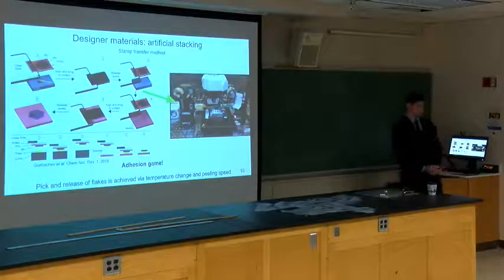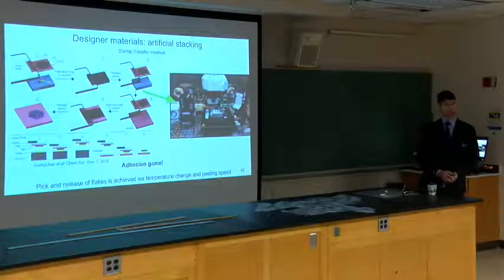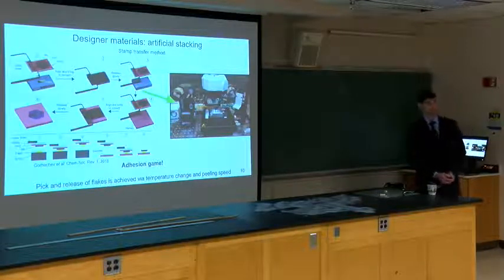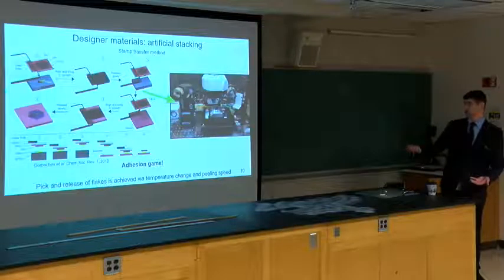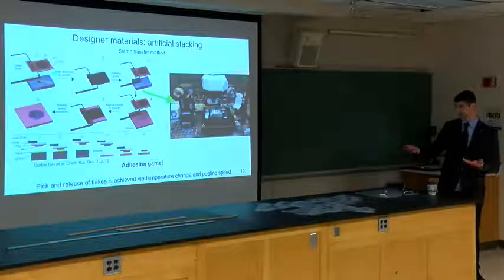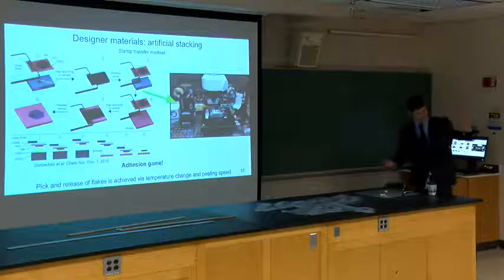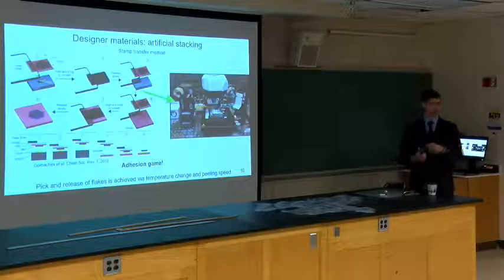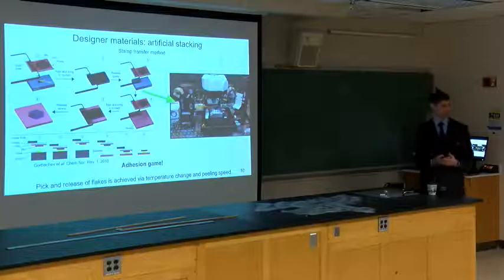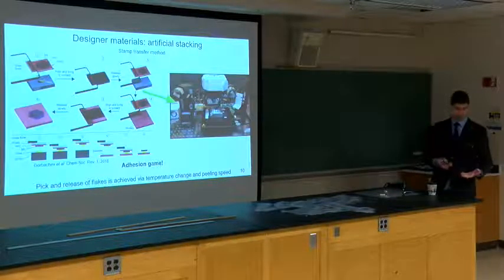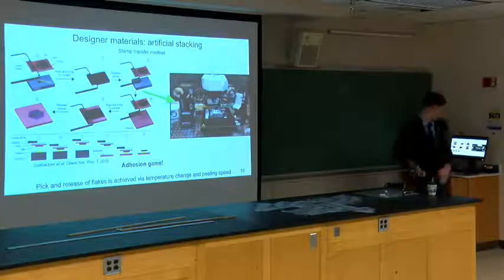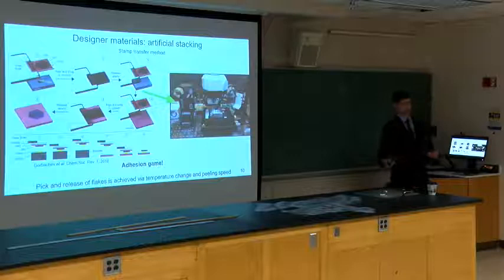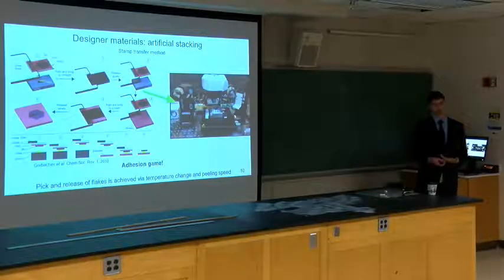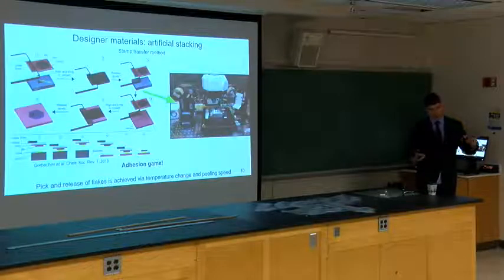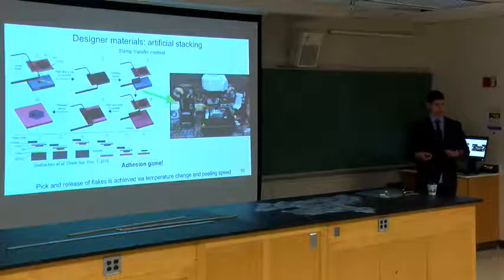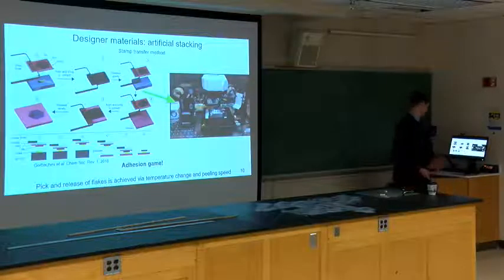So to make these designer materials that I showed two slides earlier, it's pretty low tech, actually. We take a microscope and we use a stamping process, with a PDMS stamp or some type of polymer, where we have a glass slide and we're just picking up material after material. We use the Scotch tape method, a little more sophisticated than that, but that's the gist of it. Once we exfoliate it onto a material, we use this to combine the materials. And I say it's a game of adhesion. You're basically operating these polymers right around their glass transition temperature, and you can lower or raise the temperature to make the adhesion either stronger or weaker between the substrate or between the relative crystals you're trying to pick up.